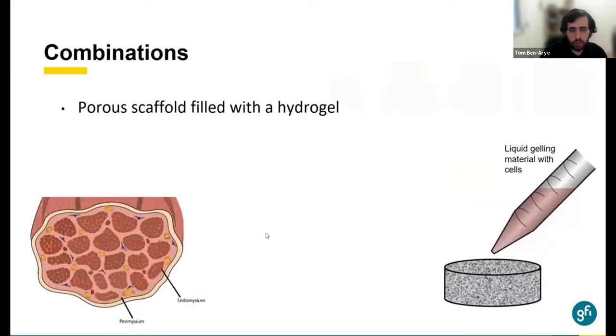Something to consider that we saw before, but we didn't mention it, is the combination of the different scaffolding types. For example, using a combination of a porous scaffold and a fill-in hydrogel, generating an environment that mimics the perimysium and the endomysium. That's what we used in the TVP scaffolds. We use TVP as a perimysium-like structure, and inside it we used fibrin gel so that the cells can grow inside the pores of the scaffold. And that's something that should be considered.